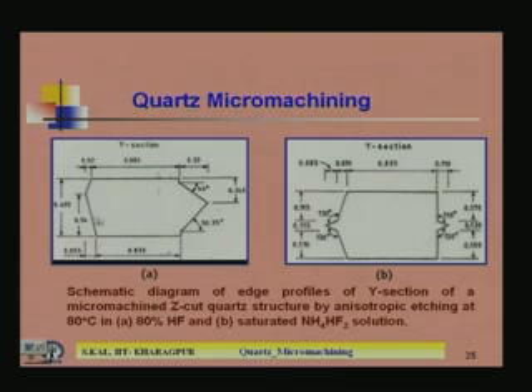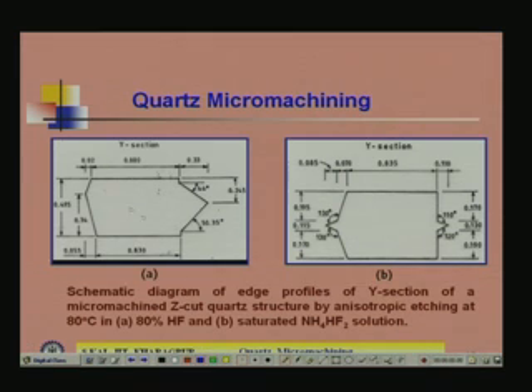So, here two crystals are shown. In A, you can see this is the masking layer. So, now it is going to etch here. So, you get here some kinks. This is the kink, here this is the kink, or it is known as the facet. It is because of the regular structure of the crystal, that is the quartz crystal, it will produce like that. So, this kind of thing will disturb your performance if you use that kinked quartz structure in your piezoelectric sensor. Performance will have a lot of deviation.